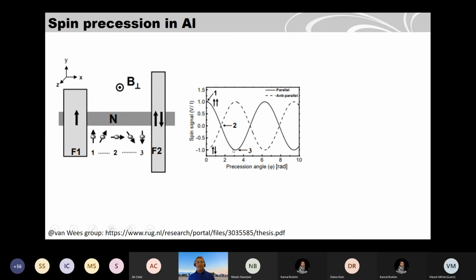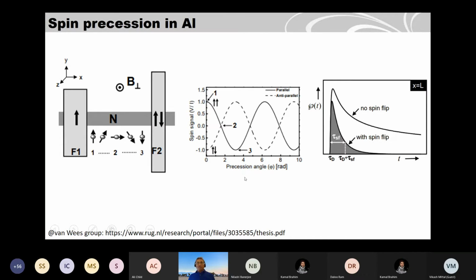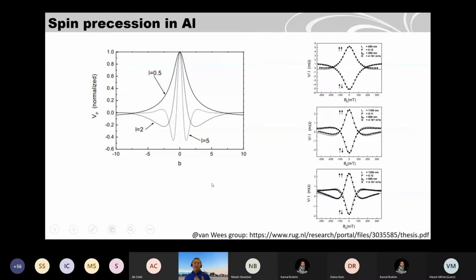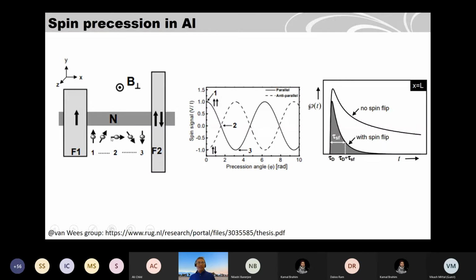So you can do both for parallel and anti-parallel. For parallel, you will see such behavior. And for anti-parallel, you see these dotted lines. So the spin signal should behave like this with angle. But what happens is that you also have spin flip scattering in your material. So you have a spin lifetime in your material. If you consider that, your spin signal will decay much faster. So you will see a signal when you apply a magnetic field, but it depends also on the channel length because spins are precessing while they are moving. So if you detect here, for example, spins are not completely out of plane. But if you detect here, they are 90°. But if you detect here, it's out of plane.